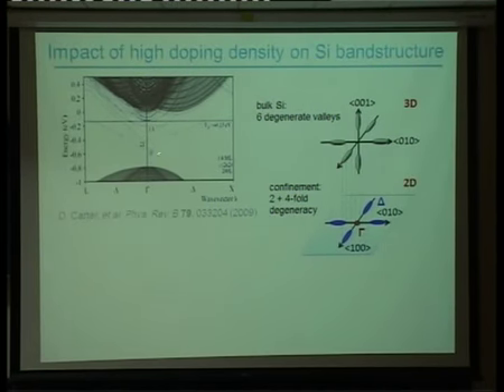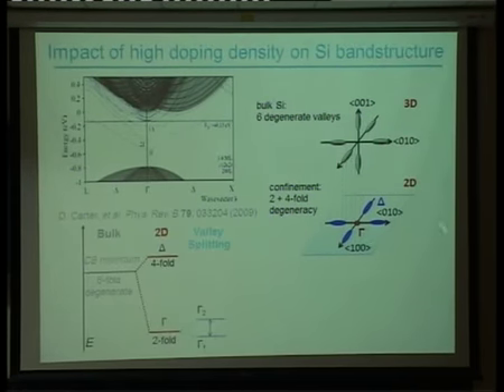So you can see here's our 1 gamma, 2 gamma, and 4 deltas. Because of the very strong vertical confinement, we get valley splitting of these gamma states here. And this valley splitting is of order of tens of meV. And that's basically what we're seeing up here. So it's basically an impurity band that we bring down below the Fermi energy. And essentially all of these bands are occupied because of the very high doping density that we have.